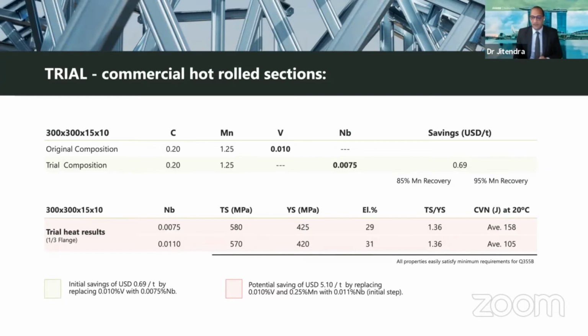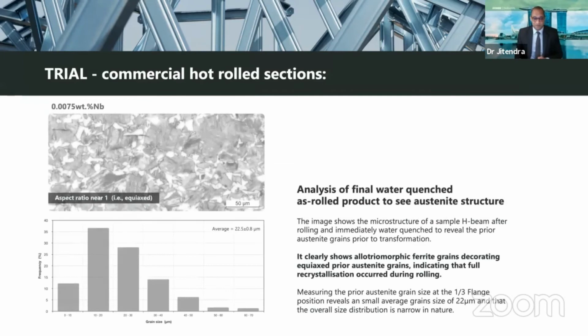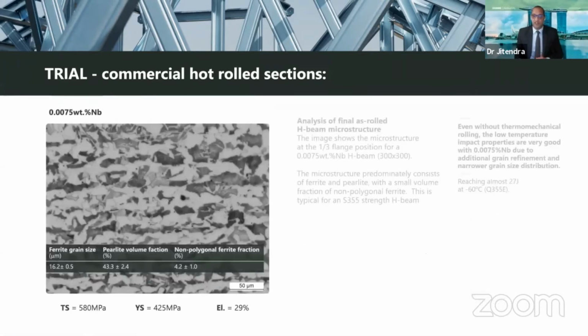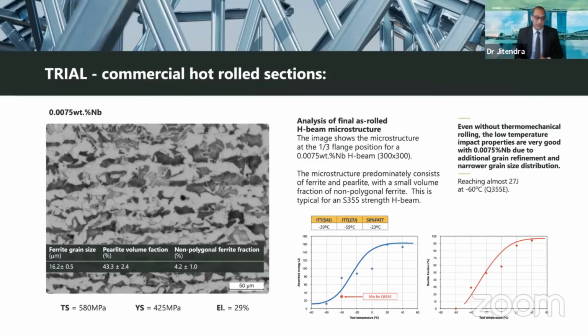What was also interesting with this particular example was that the low temperature performance, the Charpy impact values, are also very good. And you can see here from the bottom that the mechanical properties are comparable to their original commercial alloy design. We managed to quench a sample of this steel straight after rolling just to look at the microstructure. And what we found was that the aspect ratio was near one. So we weren't getting any pancaking, which we wouldn't expect because we're finishing quite hot, typically for sections near 950 degrees centigrade. But what we did find was the distribution was slightly to the left. So it meant we had a narrower distribution and a finer grain size that had been recrystallized, which then led to a slightly higher increase in strength, which allowed for the reduction in manganese content and also the vanadium content.